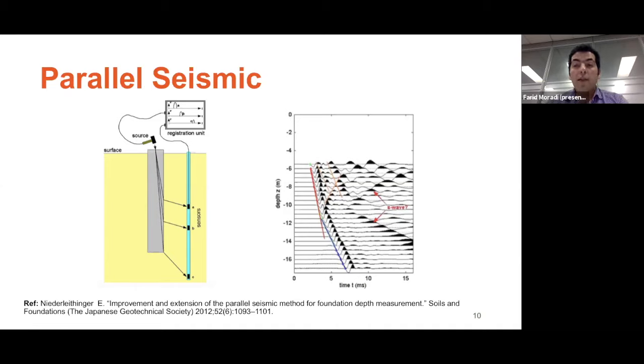It's very good for finding the pile toe, but for integrity testing, sometimes it's tricky and difficult to interpret the results, because your signals, the stress waves, travel in at least two environments. One of them is the concrete, the other is the surrounding soil. We don't know which path the signal collected by your transducer traveled. If you see some sign of an issue, let's say a defect, we are not very sure whether the defect is in the surrounding soil or directly in the concrete. But for measuring the length of existing piles, it's one of the good tests.